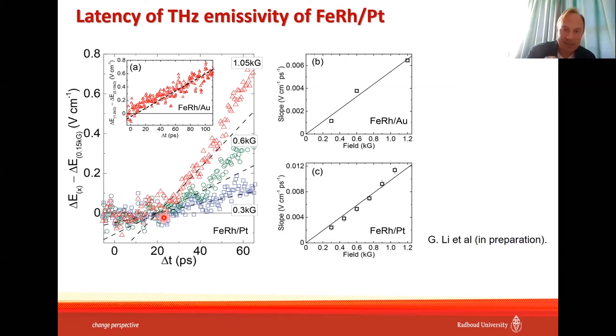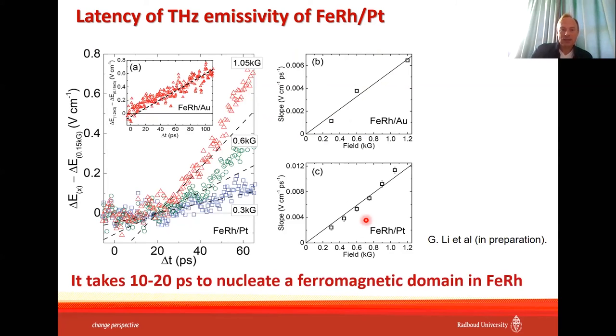And so that means there is no emissivity. You can imagine there is a pump, it comes to the sample and does something with the sample, causes whatever changes, a structural transition whatsoever, but the nuclei start to emit THz radiation, meaning they become ferromagnetic, only after 20 picoseconds. Then there is a slope again, and this slope linearly depends on the applied magnetic field. So it takes 10 to 20 picoseconds to nucleate a ferromagnetic domain in iron rhodium. That is the conclusion that we can draw from this measurement.